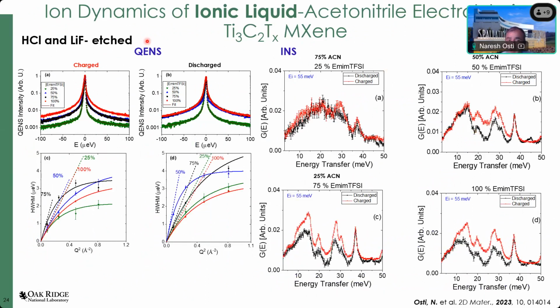Then we moved to the dynamic aspect and the inelastic neutron scattering aspect. We collected the quasi-elastic neutron scattering signal from those systems in both charge state and discharge state. And as before, we extracted the half width at half maxima from both systems, from which we extracted the diffusion coefficient. That diffusion coefficient mostly comes from the slope of the half width at half maxima dependence on Q. As you can see, the diffusion coefficient is higher once you have 25% of acetonitrile in the charge state, and the maximum moves to 50% in the discharge state. That's what we found from the points.